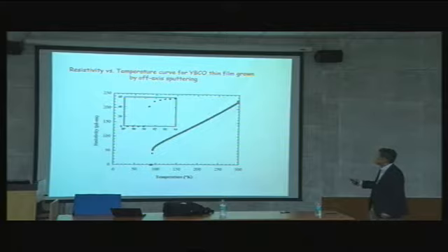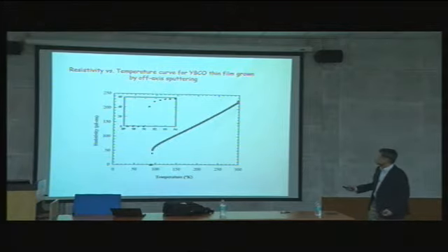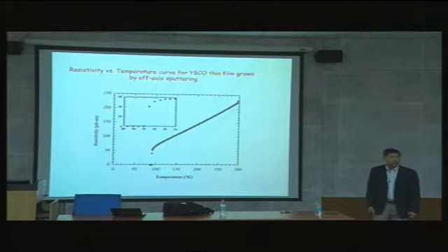Okay, so this is actually the superconducting transition temperature. You can see how sharp the transition is for the sputtered yttrium-barium copper oxide thin films. You can see that 91 Kelvin is a very high Tc, and this is as good as one of the best thin films you can grow. And how sharp the transition is, you can see from here to here, a very sharp transition. And the normal state resistivity is quite good.